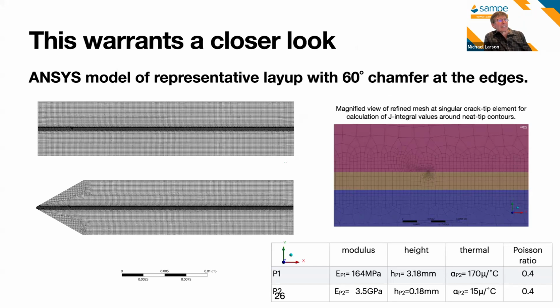So we actually did a detailed ANSYS finite element model for, again, the same types of a stiff and a compliant plastic being bonded together in layers. On the right is the inset of a detail of where a crack, which I say crack, and of course I mean a delamination leading edge appears. And we're going to use the J integral to take multiple contours around that tip to look at the amount of energy available for extending a delamination.